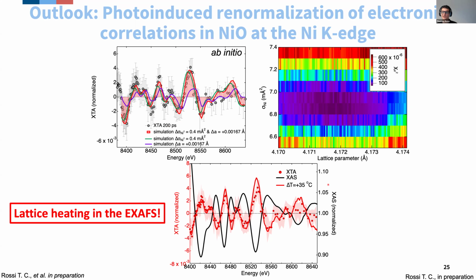So we get this great plot of a minimization of a chi-square to actually establish how the lattice parameter changes and how much the Debye-Waller factor changes with ab initio calculations. And we were also able to reproduce the pump probe by these complementary measurements of lattice heating. And you can find out that, for instance, in this case, a lattice heated up by 35 Celsius actually reproduced really well the signal you see in the EXAFS.